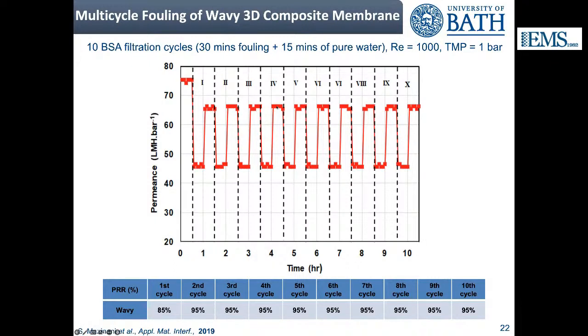So this is really interesting, because essentially you have a membrane that, once you form an initial fouling layer, doesn't foul anymore. And that is because of the wavy structure. This is very interesting, and it could be a way to significantly extend the performance of a membrane process using a very common material like PS, but only giving it structure. If you want to know more about this work, this is a paper we published in Applied Materials & Interfaces in 2019.